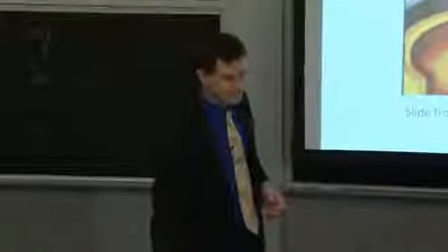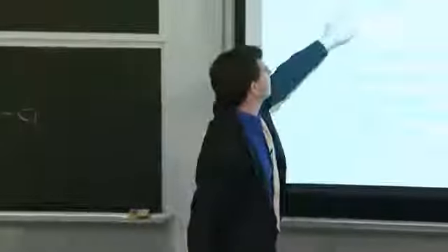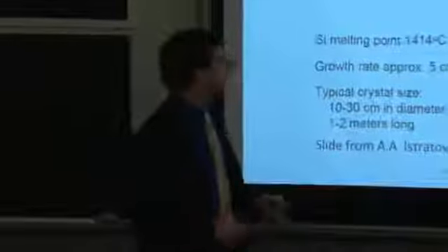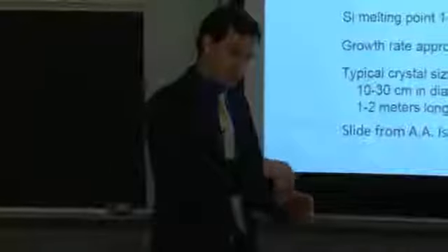And the other is, what then does control the diameter? Because I've heard about 12-inch wafers versus like 18-inch wafers. Sure. So one of the things that controls diameter is the balance of heat extraction. Right? So if you cool something down, especially molten silicon, it will freeze, it will grow. If you heat it up, it will shrink. So that's one of the components that controls the diameter. The pull speed and how you grow that shoulder, essentially how you heat up the material and how fast you pull at those initial stages, also dictates the diameter.